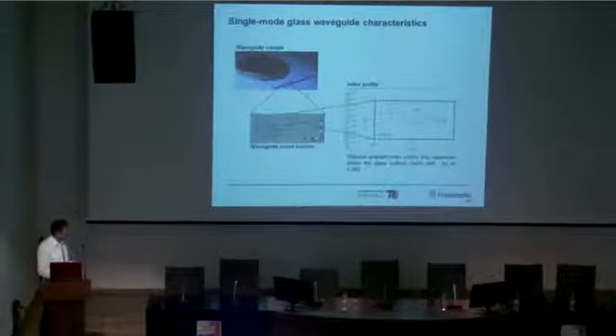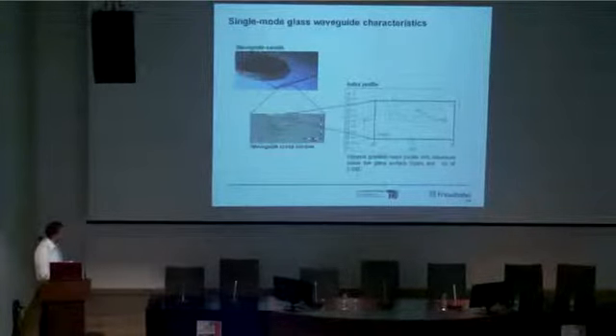If you have a closer look at the edge of this waveguide slide here, we have the glass material. It is unchanged, but we have only changed the glass very close to the surface. We have increased the refractive index, and we have these waveguides here. In this case, we have a pitch of 125 microns. And because of the diffusion process, we get a gradient index profile, and this profile is about 5 microns below the glass surface, and has a refractive index difference to the bulk glass of 0.003.